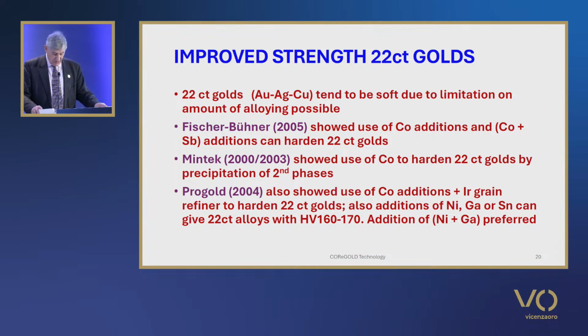91.7% gold, 3.84% silver, 1.96% copper and 2.5% cobalt alloy, which suggests that their hard 22-karat gold alloy is hardened by cobalt alone. They show a micrograph of cobalt precipitates growing on the grain boundaries and finer precipitates within the grains, but at that stage they hadn't identified what those finer precipitates were.